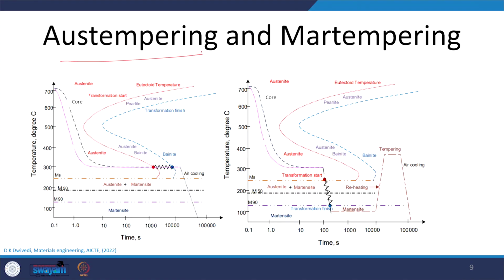Austempering and martempering are these two other important heat treatments. Austempering is done primarily to form the bainite. Okay. So, what is done? The component is quenched just above the MS temperature, and it is held at that temperature for long, so that whole austenite transforms into the bainite, followed by air cooling. This is what austempering is.